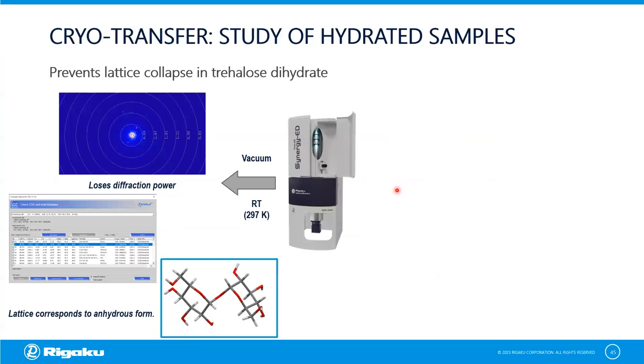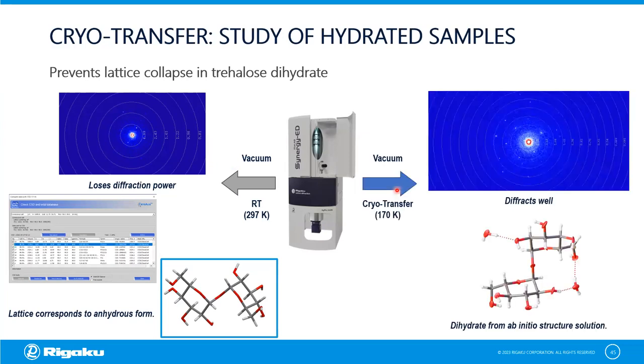So I mentioned cryotransfer early on. I wanted to make sure that I touched upon that. So here's an example of trehalose dihydrate, which, inserted into the high vacuum system of the Synergy-ED, loses water, and we see the anhydrous form at much lower resolution. If we cryocool the sample before insertion into the Synergy-ED, and expose it to the vacuum at 170 K, we preserve the water in the lattice, and we get the original structure, the dihydrate, as would be seen at room temperature and room conditions, providing a much better overall structure.